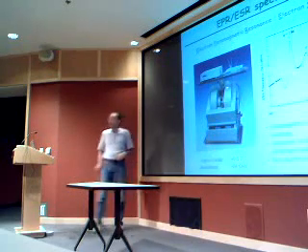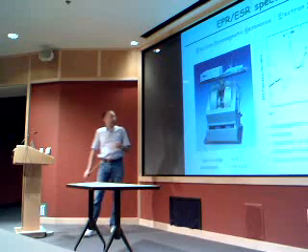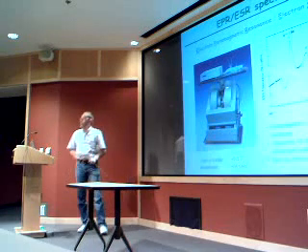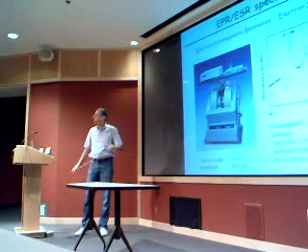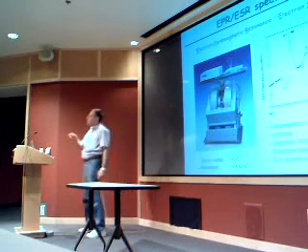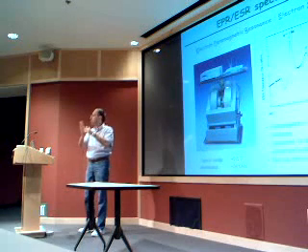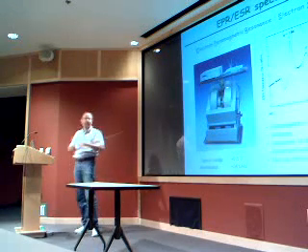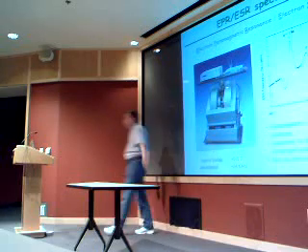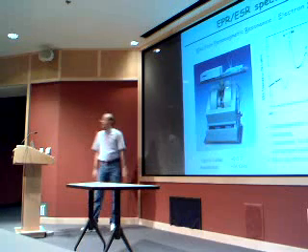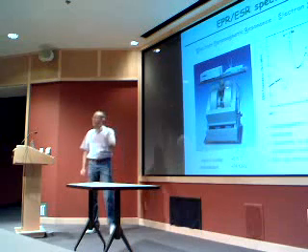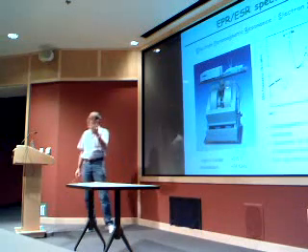And it is important because the resonance of the spin is very sensitive to the local geometry. For instance, it can give you the local symmetry of your defects. Imagine you put some gold atom in silicon. By measuring the components of the g tensor, this can tell you: is this gold atom sitting in an octahedral position? Is it sitting a little bit off-site or not? So it can give you the symmetry. And it is also sensitive to the electronic structure. I will show you later that you can basically measure your wave function using EPR. And the g tensor is basically probing, for instance, the crystal field.